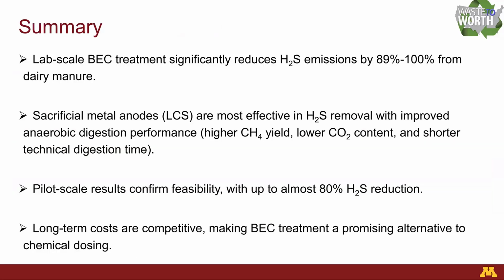So to summarize, our lab scale BEC treatment significantly reduced the hydrogen sulfide emissions by over 90% from the dairy manure. Sacrificial metal anodes, low carbon steel, are most effective in hydrogen sulfide removal with improved AD performance. Our pilot scale results confirm the feasibility of the system, with up to almost 80% hydrogen sulfide reduction. It's a little bit lower than our lab scale test. The long-term costs are still competitive, making the BEC treatment more promising compared to chemical dosing.